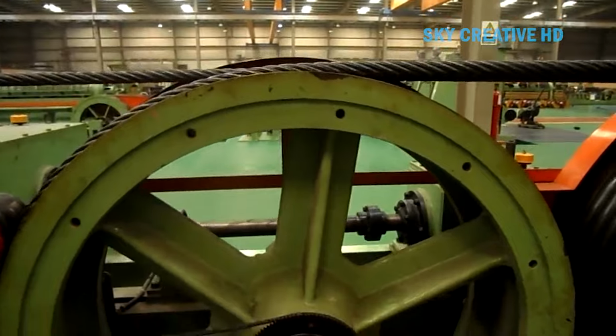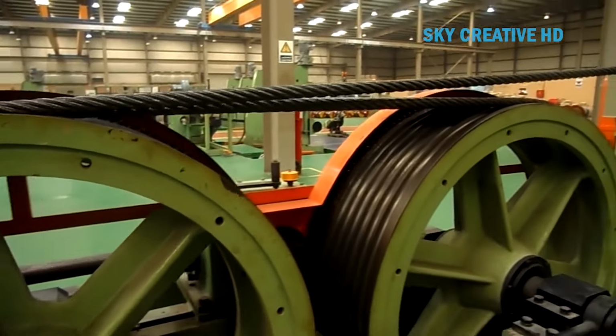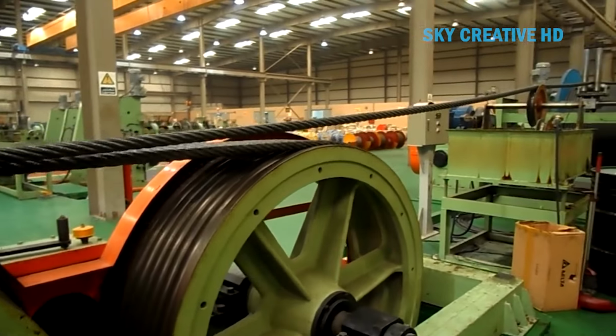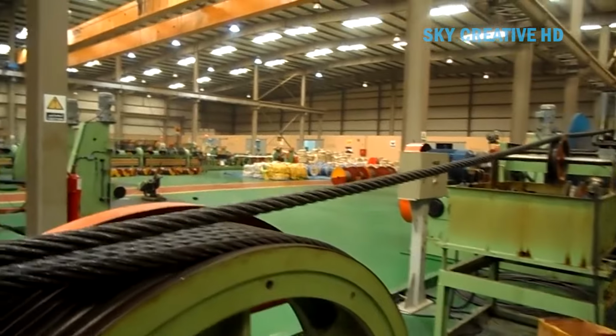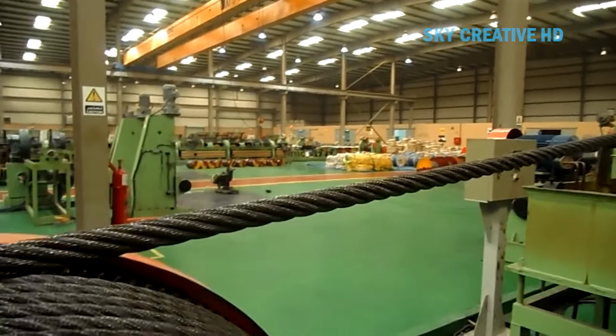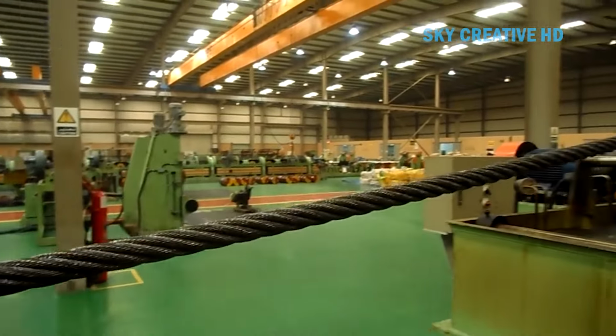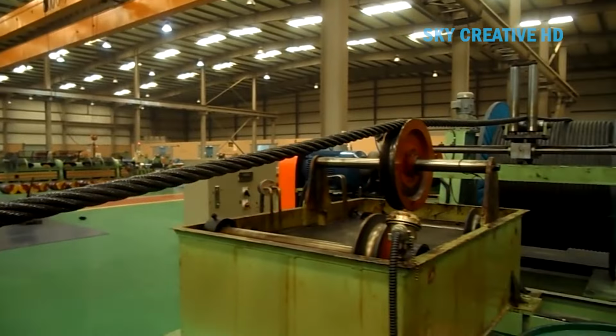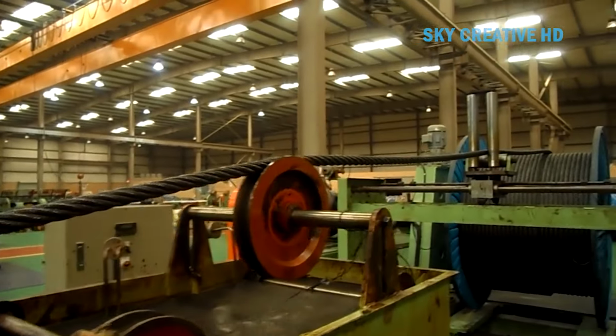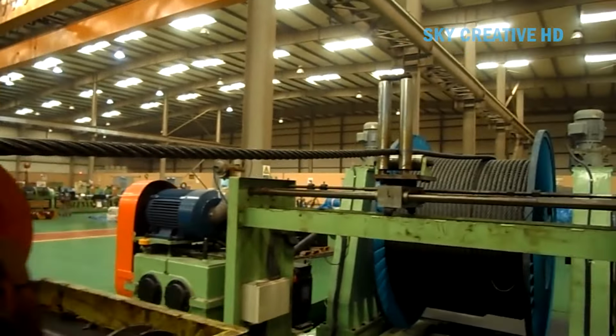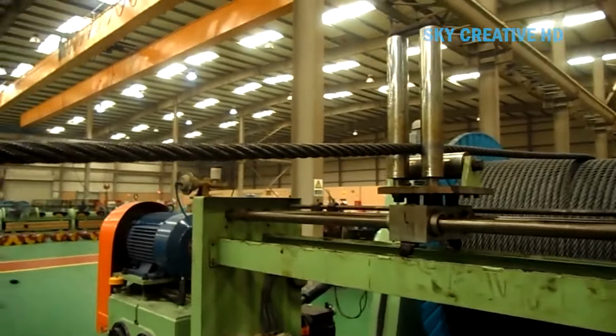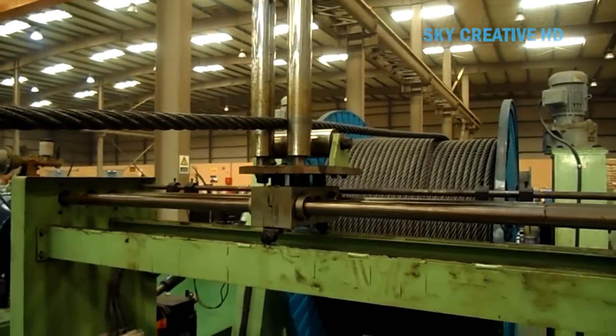The closing operation is where rope takes final form. 6 strands, plus a fiber or wire rope core, feed into a closing machine, essentially a larger version of the strander. This machine twists the strands around the core, creating the finished rope. Post-closing treatment is crucial for drilling applications. The rope passes through a straightening die that removes residual twist and ensures straightness.